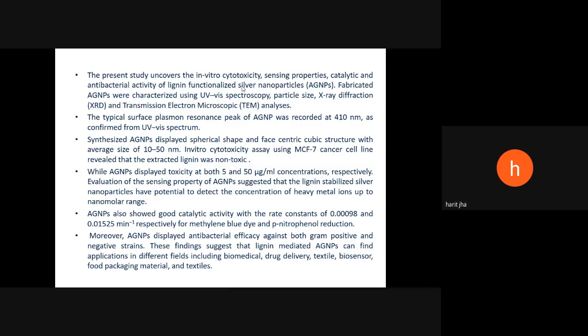We can prepare it by any of the processes, including reduction or oxidation, using any oxidative or reductive material. But the problem lies with their agglomeration and loss of the property. So if you keep them for a longer duration, the silver nanoparticles tend to lose their property. They agglomerate, that is, form clumps. So to avoid that, you need to modify them. And if you need to add some important property in that, improve their property, you again need to functionalize them. So in this particular work, we have functionalized it using the lignin, and